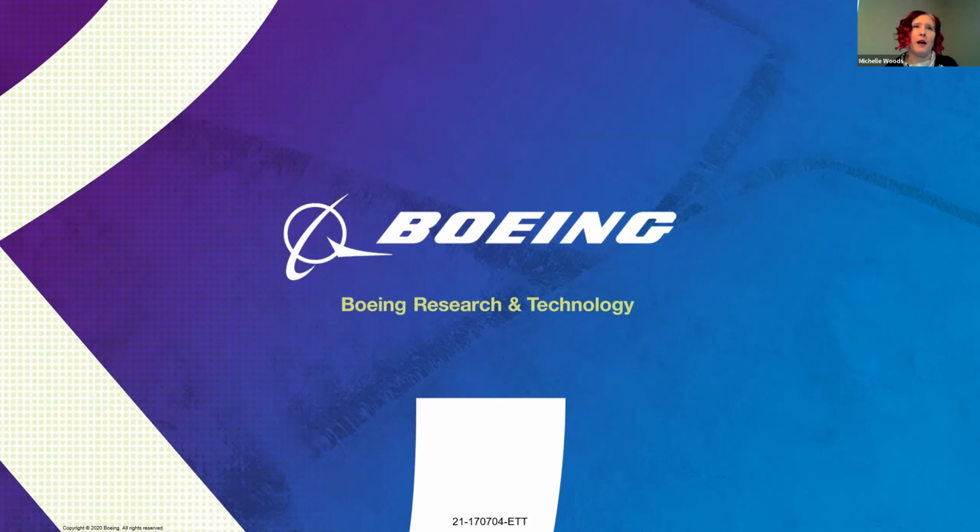It can be. I've actually been mentoring a colleague who works within the decorative laminate fabrication process. And that is one thing that we've discussed, is that printability can frequently interfere with, in particular, the material's ability to pass flammability testing as is needed in the full certification buildups. Those are competing requirements that we're trying to meet. Can we get good printability and also meet the robustness of the material, because it has to withstand a fair amount of abuse, a fair amount of cleaning, things like that, but keep the printing and that nice decorative aesthetic intact. So yes, that is definitely a concern that we've been looking at as well.